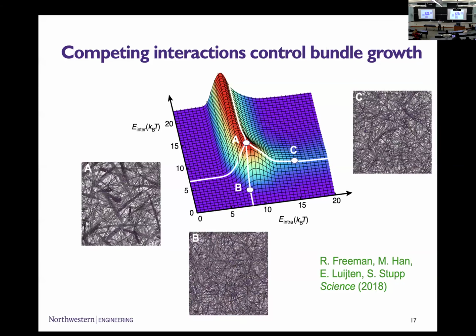And so we find, well, if you cannot pull DNA with its associated peptide out of a micelle at all, then you just get a gel. This is how any rubber is made, right? So you just are cross-linking a polymer, and there's no way to detach those crosslinks except for breaking them. But breaking them is the other parameter. That's the interpolymer interaction. And so we find that, of course, if everything is too weak, then you also form no gels, because every crosslink just gets formed and then detached. So both parameters matter, and we really find that the growth rate of these bundles is controlled by both. So that was a Science paper a couple of years ago.